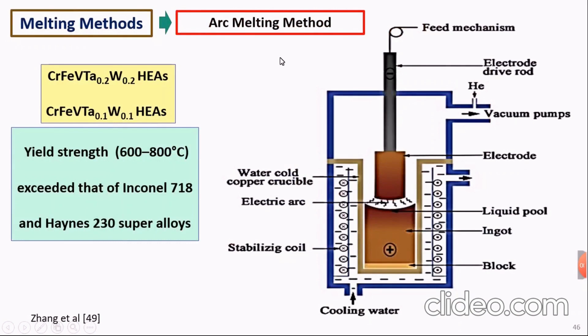The most important or the most famous melting method for high entropy alloys is the arc melting method. In this method, we have the charge placed into the melting pot, and when the electrode comes very close to the charge, the arc is generated, and this arc melts the charge. Of course, this method is suitable for high melting point elements. Like here, for example, you have chromium, iron, vanadium, tantalum, tungsten high entropy alloys. Of course, it's not suitable for the low melting point elements. The high entropy alloys produced by this method showed high yield strengths compared to superalloys at higher temperatures.